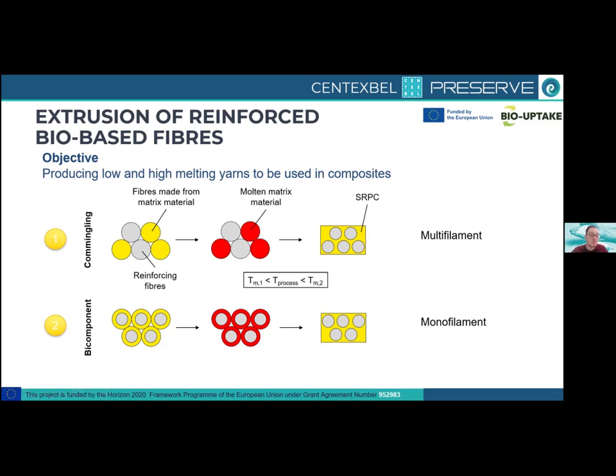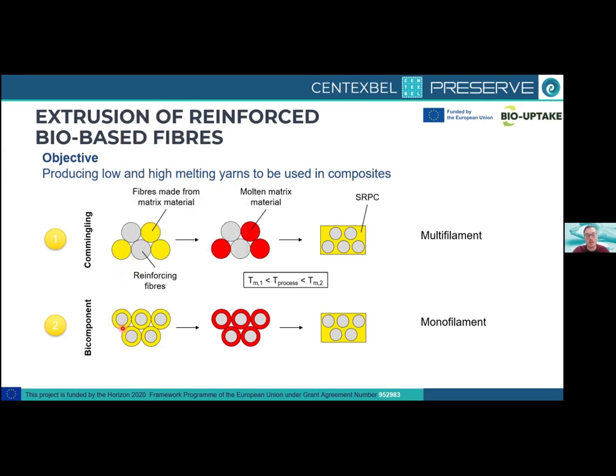The other option is by using bicomponents. So then you actually make the material together. You produce the low and the high melting yarns together, where you can create, in the center, the high melting one, so the one with the highest strength, and on the outside, the low melting one. So again, when you heat it up to a temperature that is between the one of those two polymers, you will be creating the matrix, melting the low melting one into this, and again creating the composite. The main difference between the two is that in the first one, the commingling, we use multifilaments, and in the other one, we use monofilaments. So also with the thickness of the yarns, it's a bigger difference, but we can do both at Centexbel.